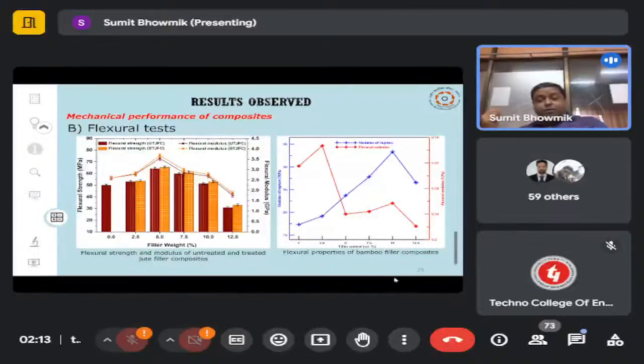Similarly, the flexural stress or bending stress has been evaluated by applying the load. In the case of jute filler, it has been observed that the flexural strength is found at 5%, whereas in the case of bamboo filler, the modulus of rupture or the flexural strength has been found at 2.5 as well as 10 percentage of filler.